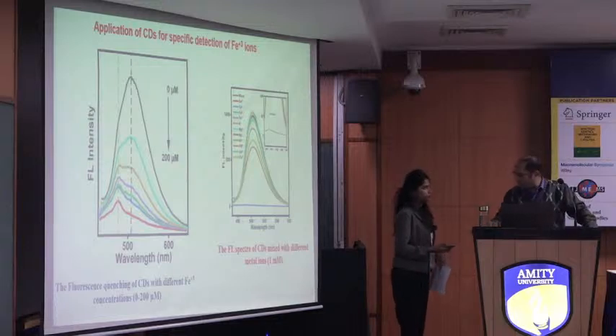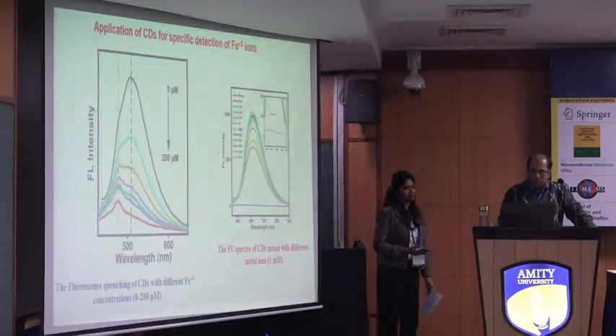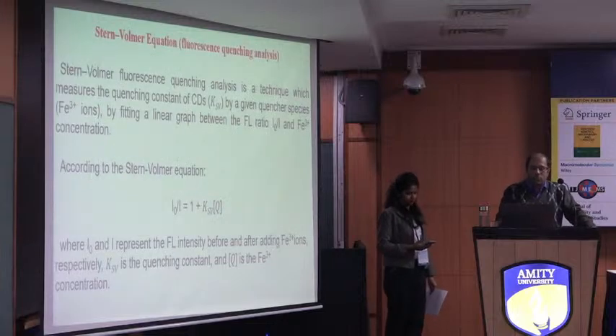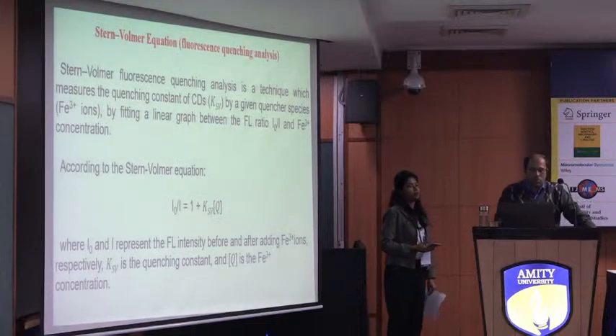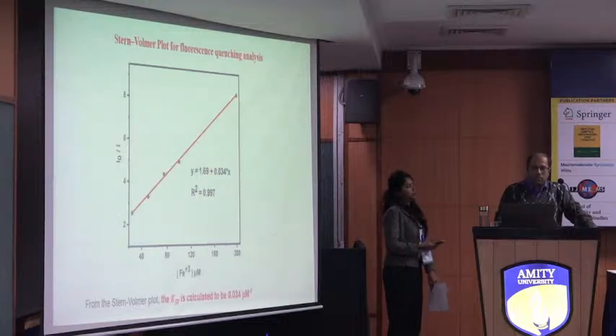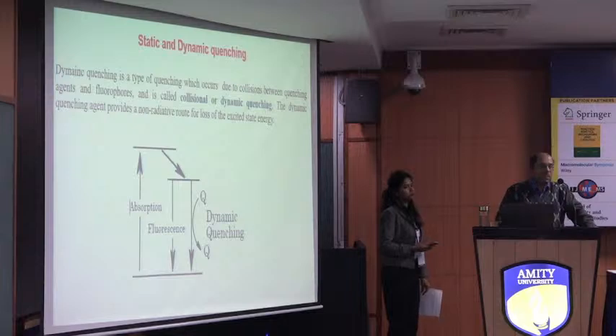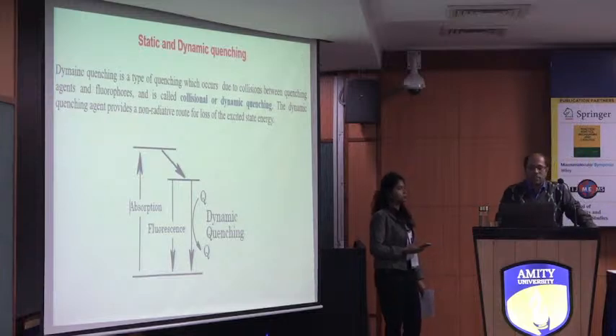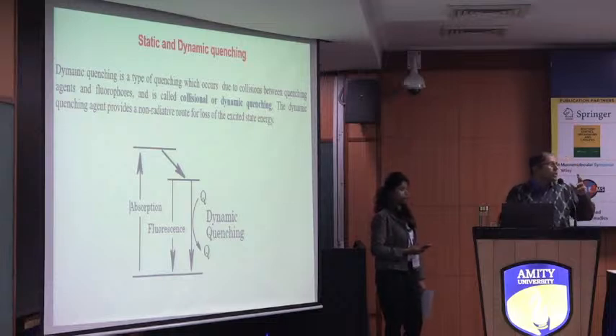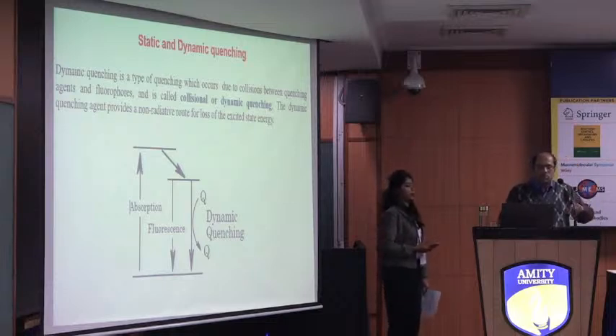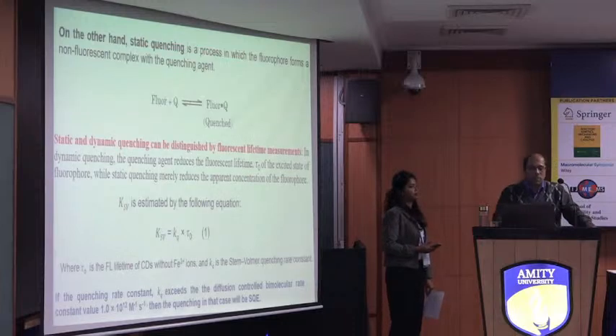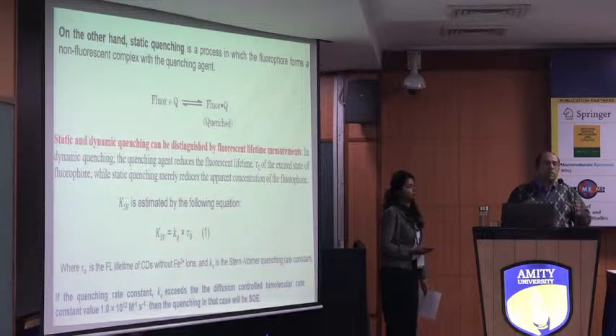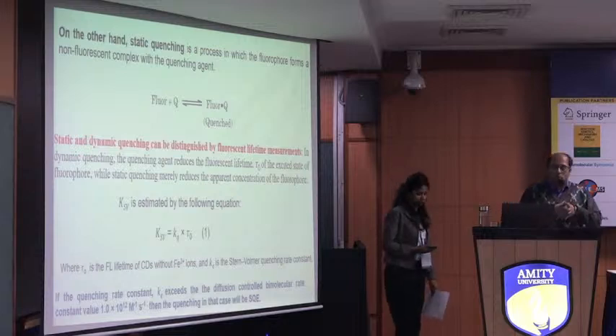As we increase the concentration of Fe3+ ions, we see fluorescence quenching, and this quenching was studied using the Stern-Volmer equation, which gives you an idea about the quenching mechanism. There are basically two quenching mechanisms, static and dynamic quenching. In dynamic quenching, generally the fluorophore, when it comes in contact with the quencher, loses its energy and quenches. Whereas in static quenching, the quencher and the fluorophore form a static complex, which is completely non-fluorescent.